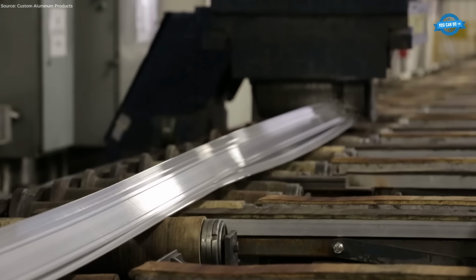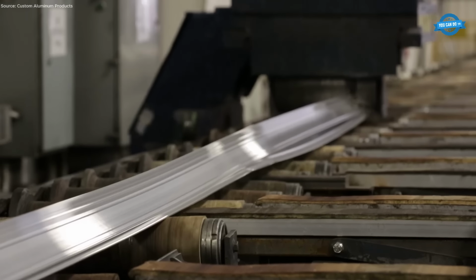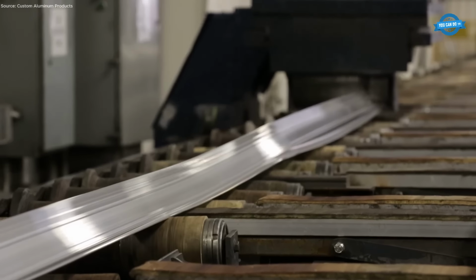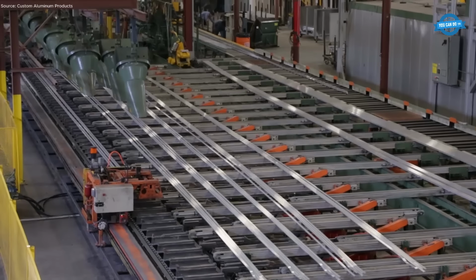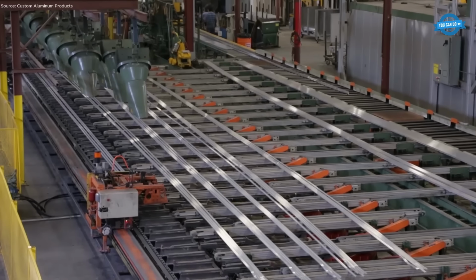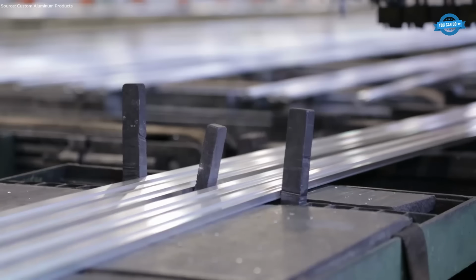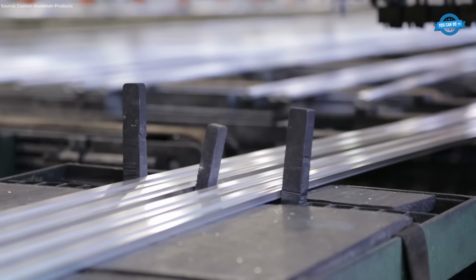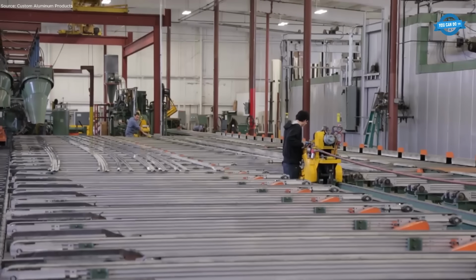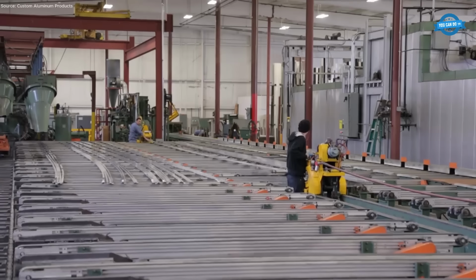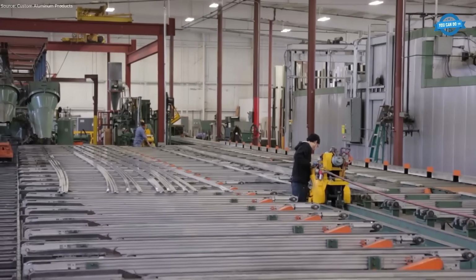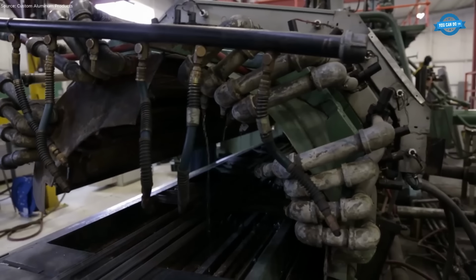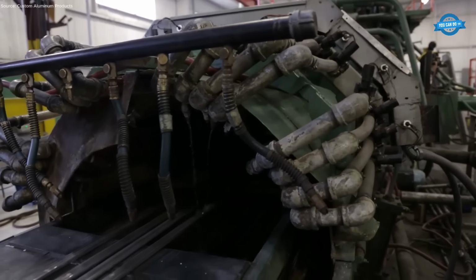Digital monitoring systems track every step, storing process recipes to ensure consistent results. From the press, a puller grips the hot extrusion, still at 900 degrees Fahrenheit, and guides it smoothly down a 150-foot runout table. Here, high-powered fans cool the profile to room temperature, achieving a T4 temper. Higher strength tempers, such as T5 or T6, are later developed through artificial aging, with water quenching as an optional enhancement.